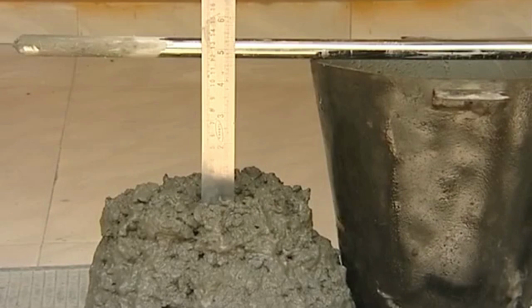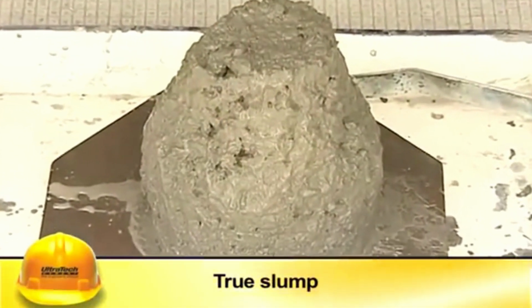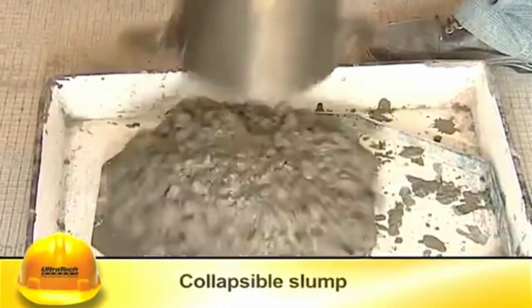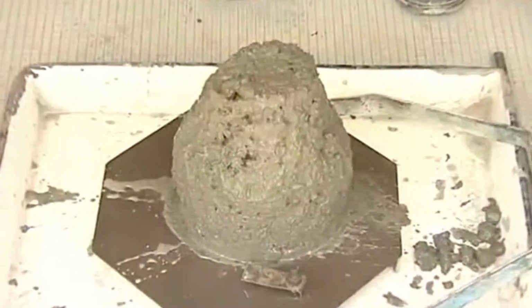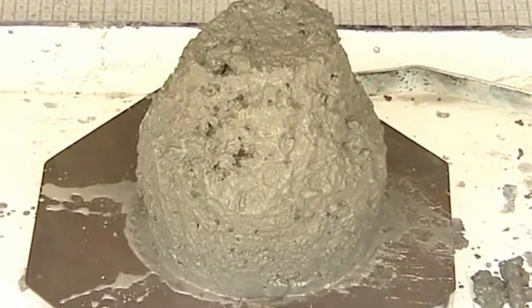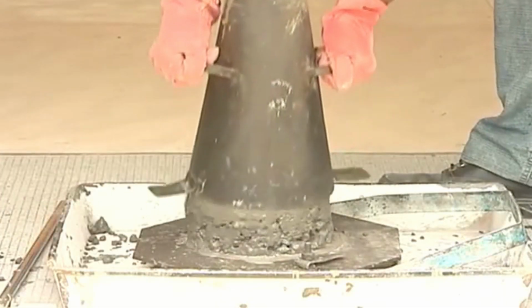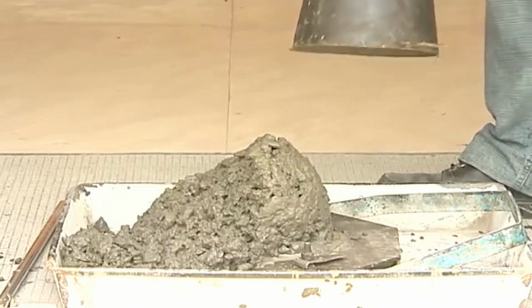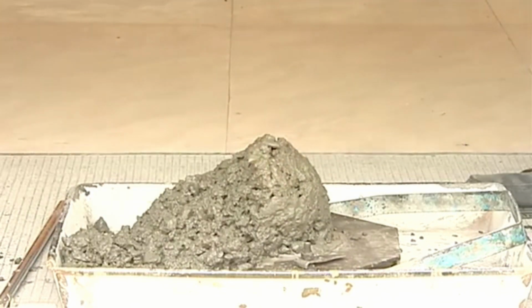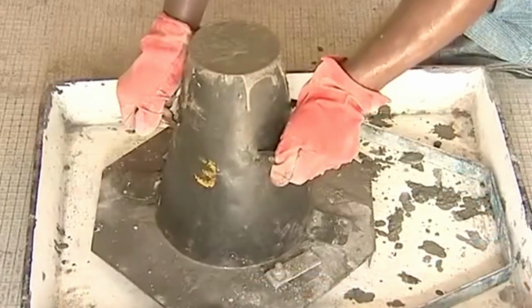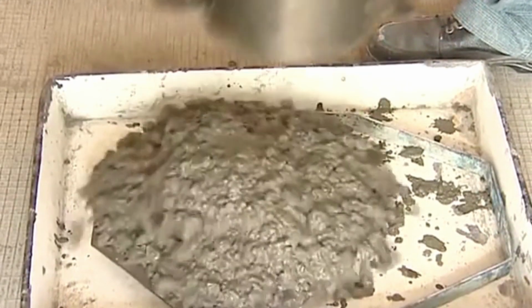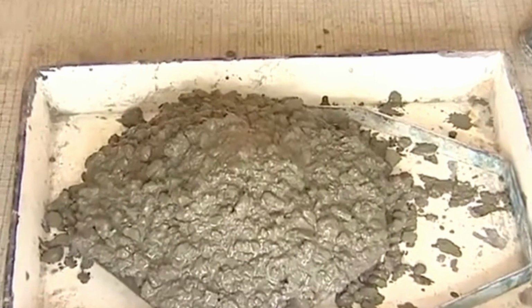It shows that due to a high water-cement ratio, the shape of the slump is not a clear dimension. It means the concrete has very high workability, for which the slump test is not suitable. And the third one is shear slump. This shape of slump is the same as shear failure of soil. This is an indication of a lack of cohesion of the concrete mix ingredients. So, a fresh sample is taken and the test is repeated.